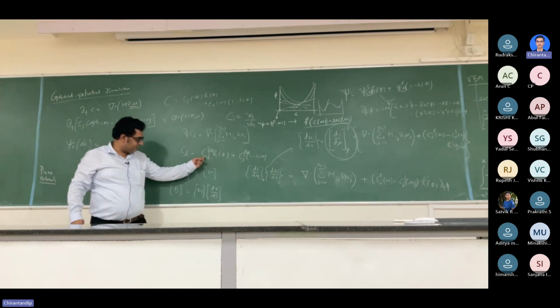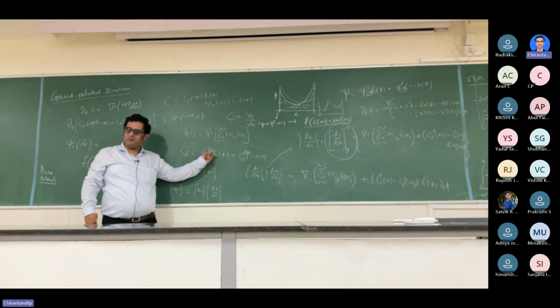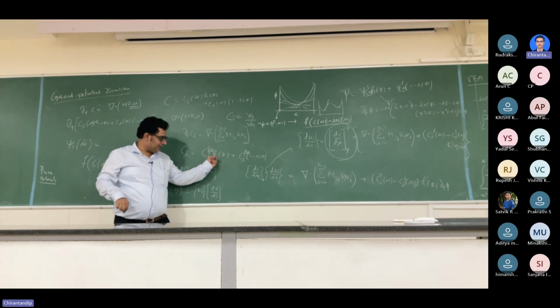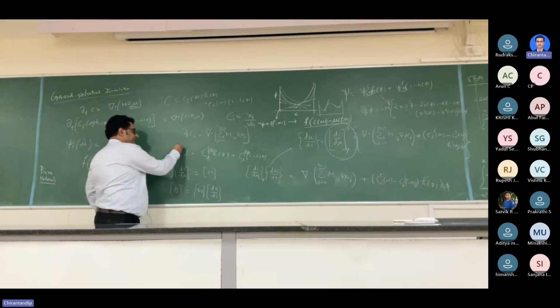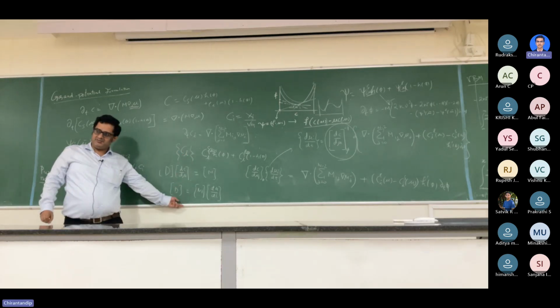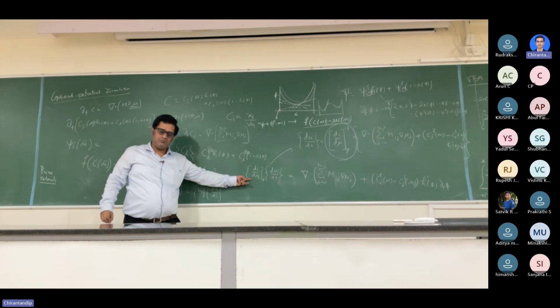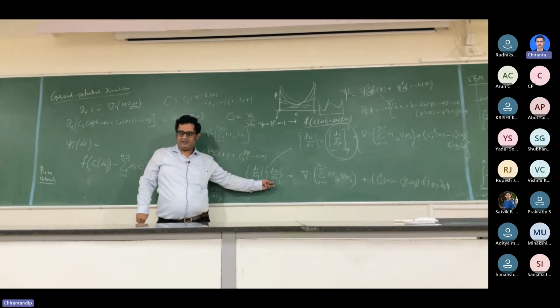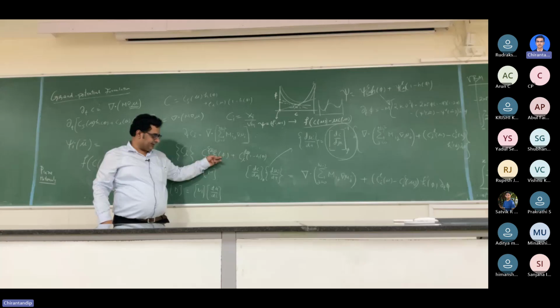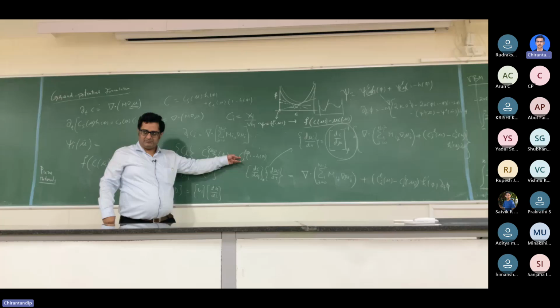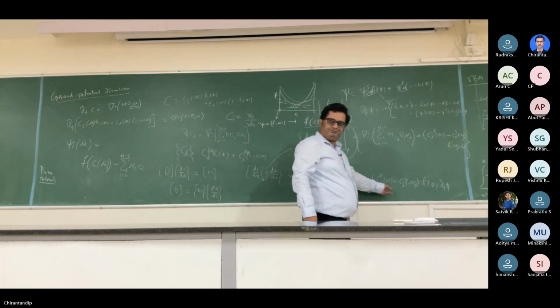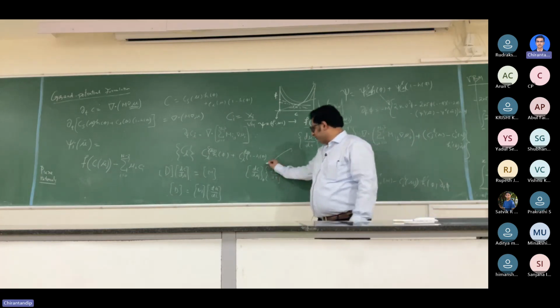So when I write down Ci as a function of mu1, mu2, mu3, mu4, mu5, all of them are time dependent, so I will take a chain rule. If I write it as a vector for all the k components, it will be a matrix multiplication of dc by dmu times dmu by dt. That's what I will do. Plus, there is another derivative with respect to phi, so it will be just ci minus cs minus cl of that component, which will turn up here.